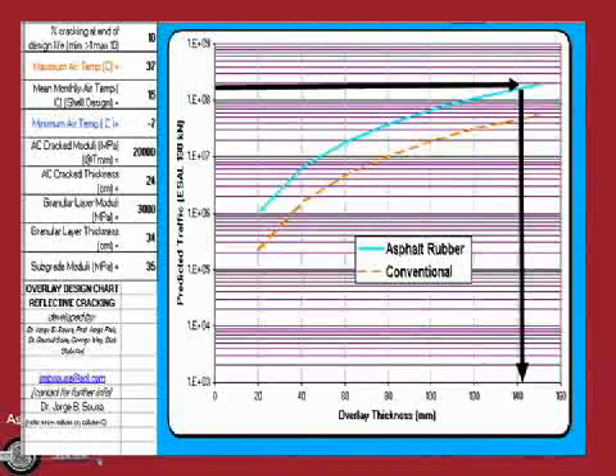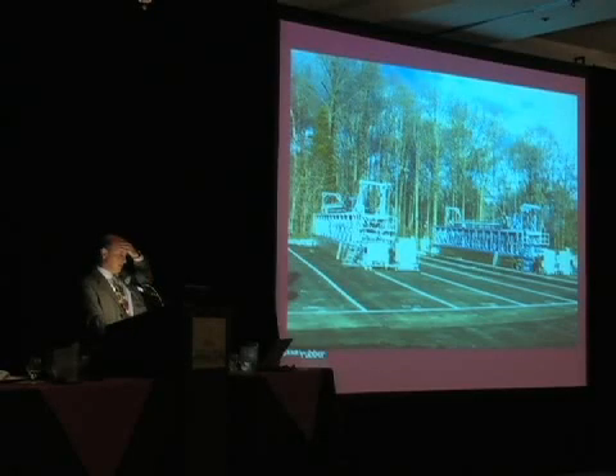Now, through that method, we have developed a method to control reflective cracking and relate overlay thickness with the number of ESALs that a certain pavement can take, as a function of the pavement conditions, layers, and moduli. And interestingly, the model tells us that asphalt rubber layers can take less thickness for a given traffic. Now, remember when I made this comment this morning regarding ALF? I think this ALF study is a fantastic basis to start thinking all new about designing pavements.